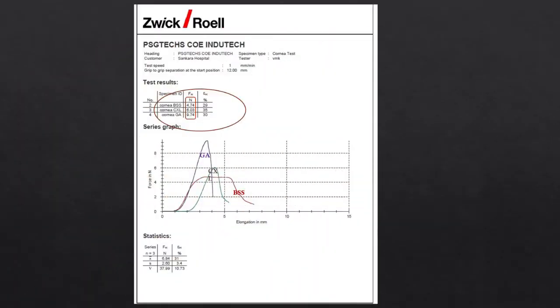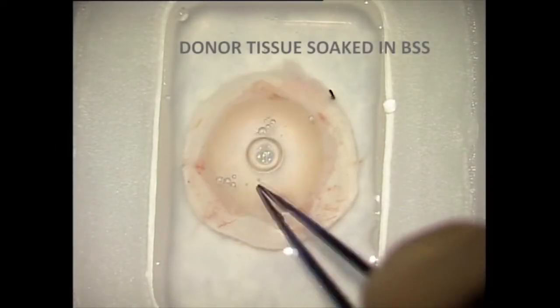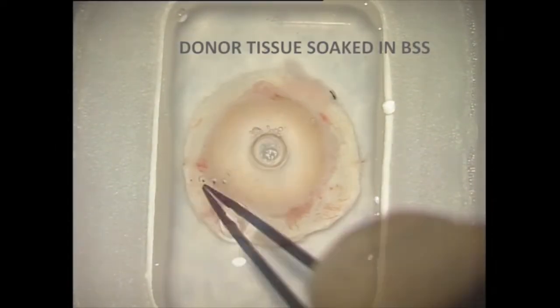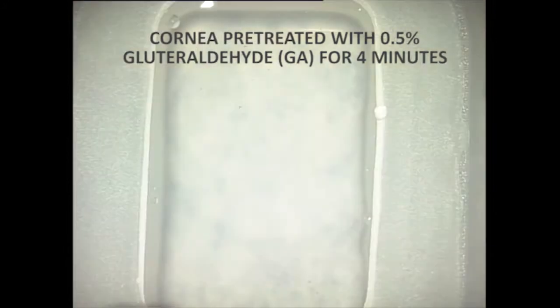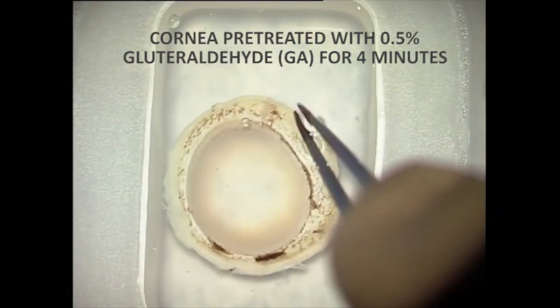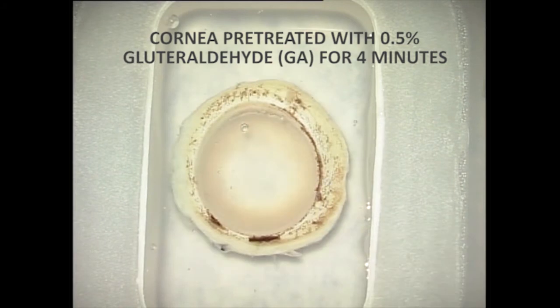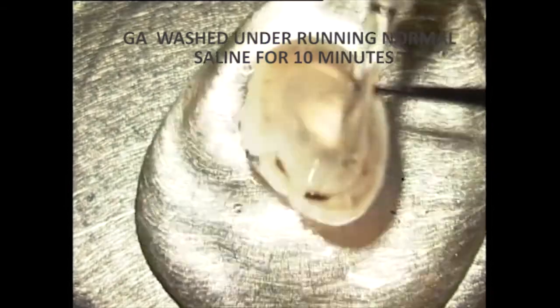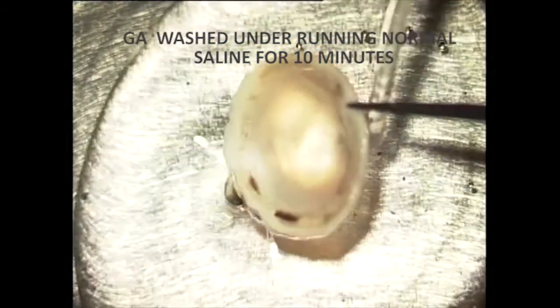This graphical representation shows that the glutaraldehyde treated tissue resisted elongation the maximum time when the separation force was applied, proving quantitatively that the GA treated tissue had the maximum tensile strength. The donor corneal tissue is first soaked in BSS for 30 minutes. The tissue is pre-treated with 0.5% glutaraldehyde for 4 to 5 minutes in an IOL tub. After treatment, the tissue is thoroughly washed in normal saline for 10 to 15 minutes.